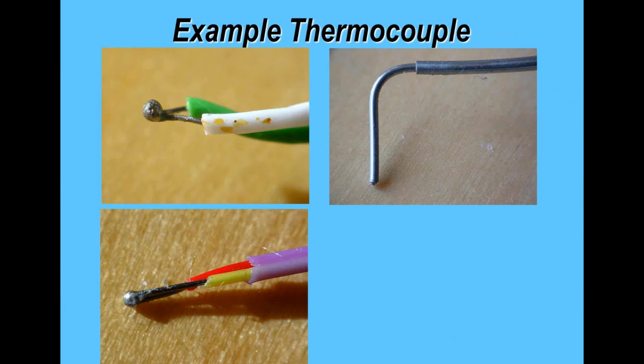I also show you a liquid probe or a solid probe. Now, what you've got there is the thermocouple is actually within that protective housing. And this is used where you're having contact with the surface you want to monitor, but not actually soldering it or sticking it or bonding it in place. And these are available from ECD, is probably the only supplier of these types of probes, and can be used for perhaps monitoring pads reflowing when the thermocouple is actually sitting in solder paste or possibly down a through hole.